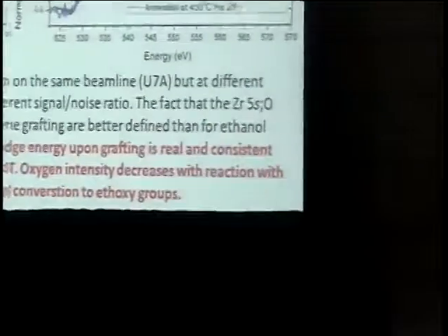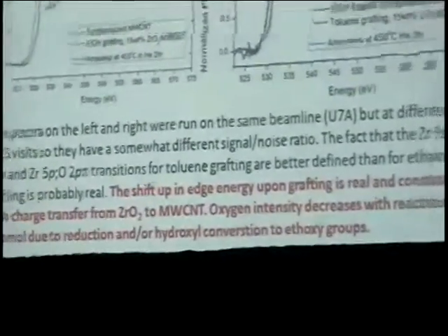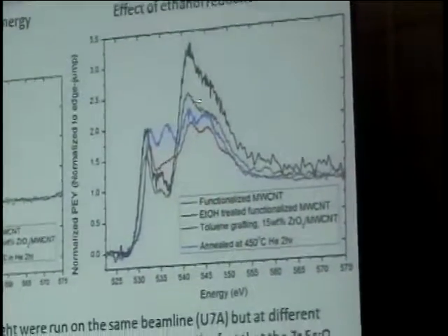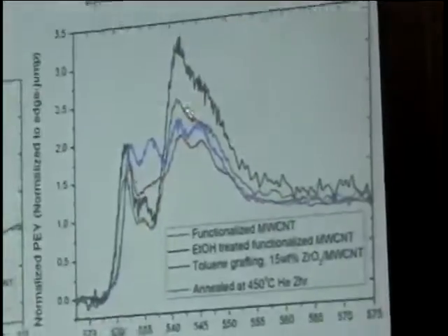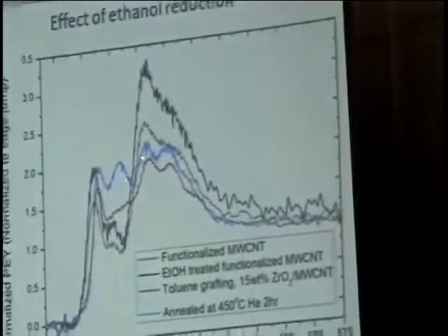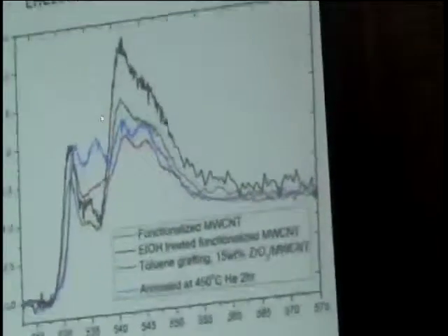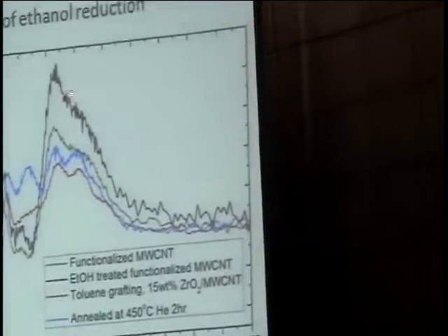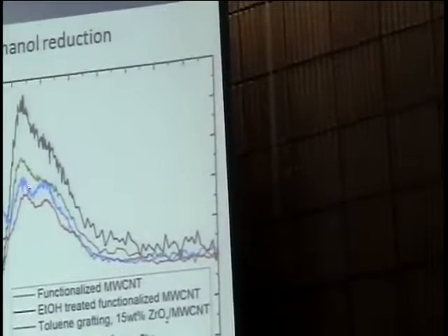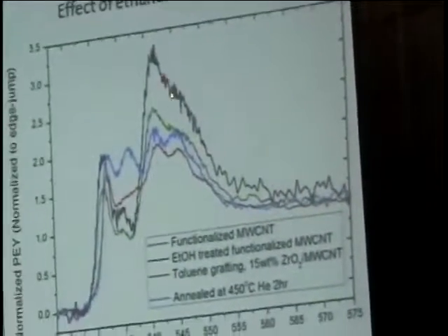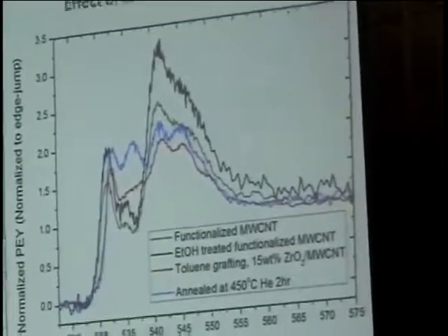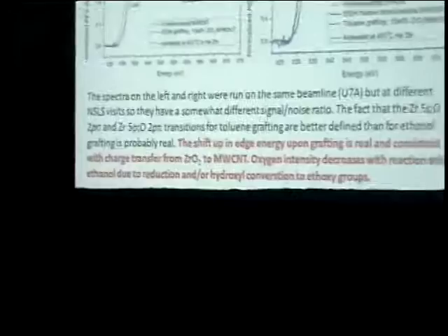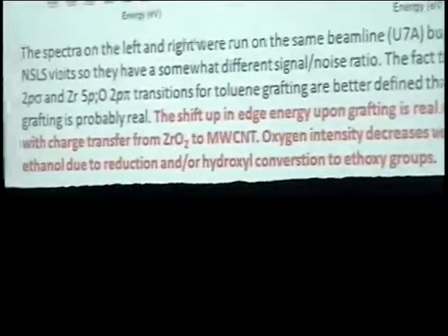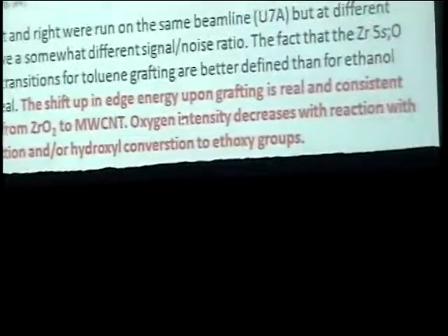So in both cases, we see a change in edge, and with respect to the intensity, we can see the case where zirconia is involved, which is this peak here. Underlying it is the zirconia, look at the blue case, and then this is the functionalized carbon nanotubes with no zirconia, and if we reduce them in ethanol, that intensity comes down. It's normalized to the edge jumps, so this is the average intensity on the oxygen per atom. So from that, I can draw this conclusion. The shift up the edge on grafting is real, and it's consistent with zirconia having transferred charge to the carbon nanotubes. The oxygen intensity decreases, the reaction